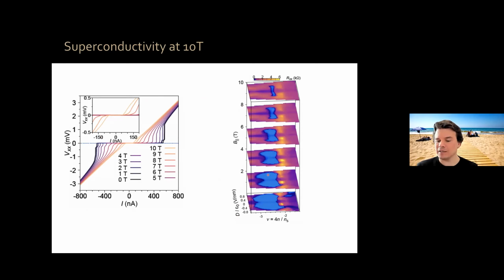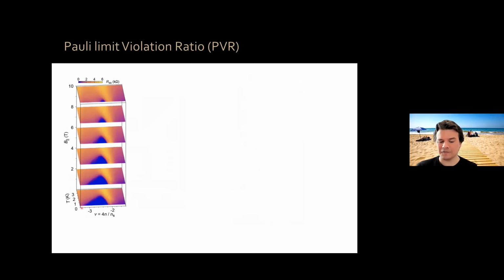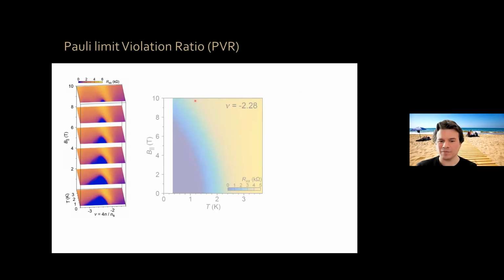Now, in order to look at how much we are violating the Pauli limit, we need to do temperature dependence measurements. So these are at optimal electric field, measurements of the resistivity versus filling factor and temperature, okay? At 0 parallel field, 2 Tesla, 4, 6, 8, 10 Tesla. So you can see that there is still a well-defined superconducting dome even at 10 Tesla, okay? We can extract the critical temperature, okay? And in particular, we can plot this resistivity versus temperature and parallel field, okay?